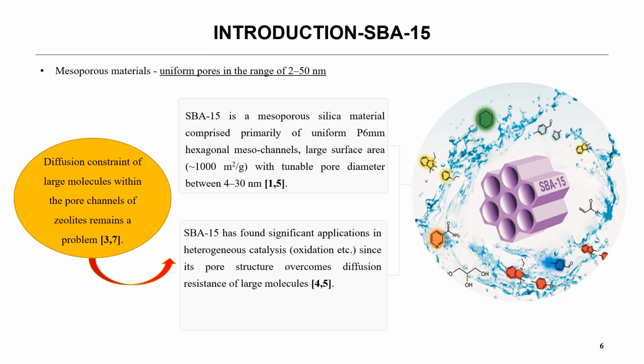As a result, mesoporous materials which have uniform pore sizes between 2 to 50 nanometers have recently drawn interest for application in catalysis. SBA-15 with its hexagonal channels, large surface area, and tunable pore sizes has been used in reactions such as oxidation, hydrogenation, etc. with interesting results. Despite SBA-15 being employed in several catalytic transformations, this is the foremost investigation for its application in the methylation of naphthalene.